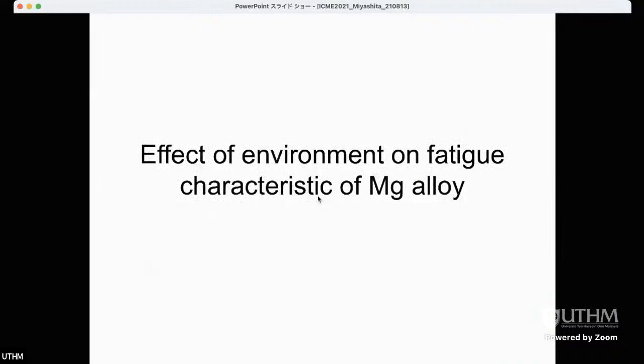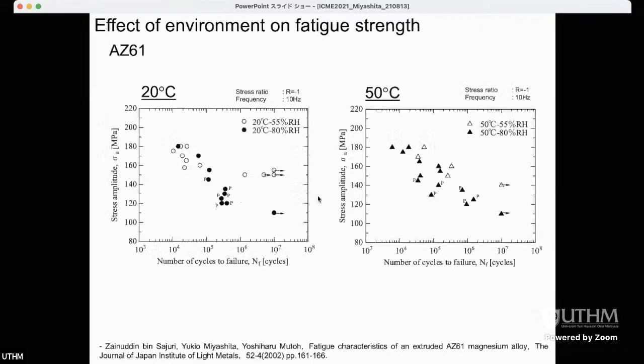So I move to the next topic, the effect of environment. We carried out a test at different temperatures and different relative humidity conditions. The temperature was changed at 20 and 50 degrees centigrade. In this case, we couldn't clearly recognize effects of temperature. However, we could recognize a quite significant effect of humidity in this test.